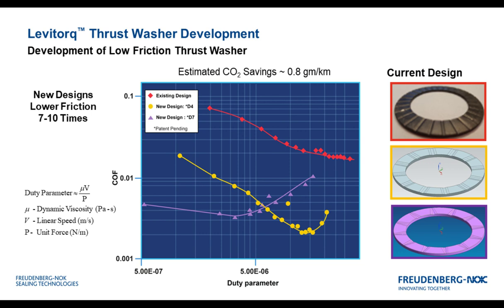And the D7 is a modified version of that design. It's more aggressive in creating fluid shear, so it has a much lower overall profile. But once you generate that shear, you can actually get higher friction because you're shearing so much fluid. So we optimize design based on application conditions and the customer requirements. But again, we're using this technology of using fluid film to generate lift on the parts and reduce friction.